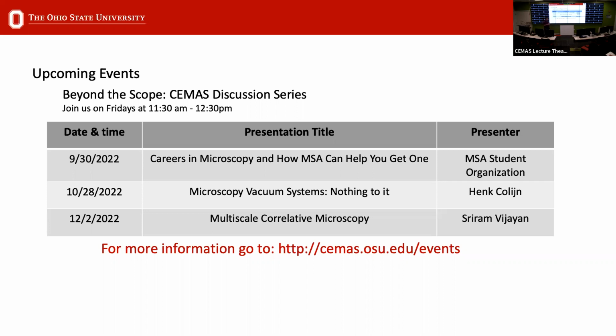Okay. So you usually always go with an ion milling after that? Yes. Even if it's not necessary, you can make a silicon sample, just plain silicon, without argon ion milling it, and just polish it using colloidal silica because it's optimized for that. But in any case, I still would ion mill that sample for 15 minutes, because that gets rid of the particles. Unfortunately, they're very hard to remove any other way. Thank you. No problem.